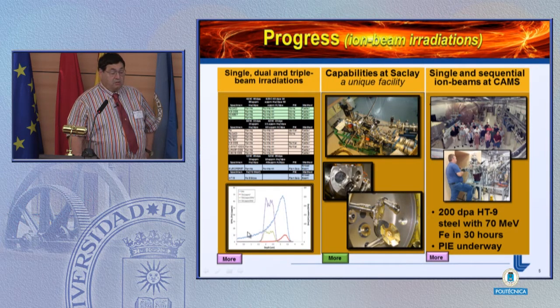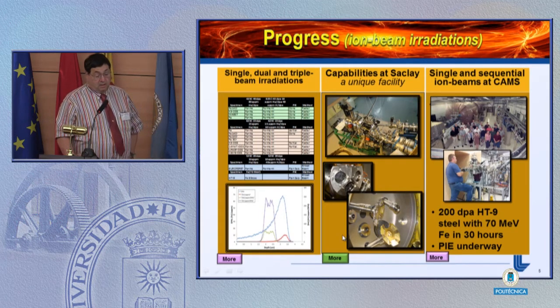Most of the irradiations are done with the helium atomic parts per million per displacements being in the range of between 10 and 40, and the hydrogen is always adjusted so that it's 4 times whatever the helium value is. So typical expectation for first wall from n,alpha and n,p reactions is 40 atomic parts per million hydrogen per dpa and 10 atomic parts per million helium per dpa.